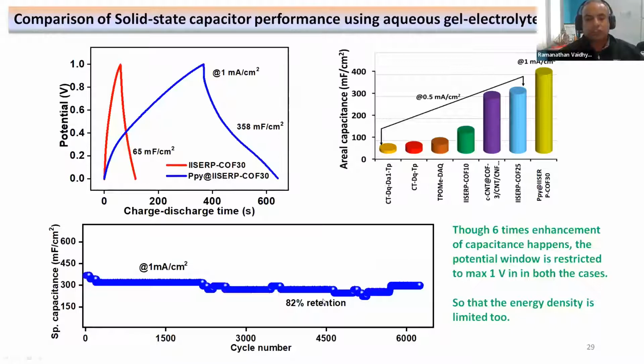82% of the charge storage is completely retained over a period of 6,000 cycles, which is very interesting. And our material stands pretty good in terms of the areal capacitance observed for this material. You can see that this is the areal capacitance of our material, which is somewhere around 358 millifarads per centimeter square. We were very excited by this, but there is a problem.